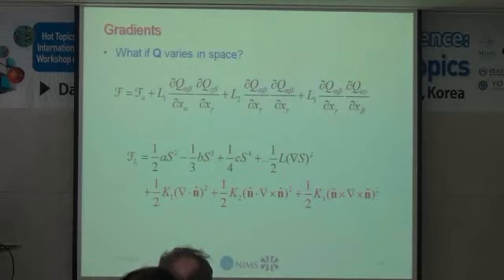Now, what happens if the order parameter varies in space? In this case, one can construct three scalar terms from the derivatives of Q, which can be put into the free energy. If you transform things back to S and n hat, it looks like this, which is just the usual Frank terms. So there's a nice correspondence here. Unfortunately, it turns out that not all three of these elastic constants are independent now. That's a bit of a problem, and people are still proposing various ways to deal with that.